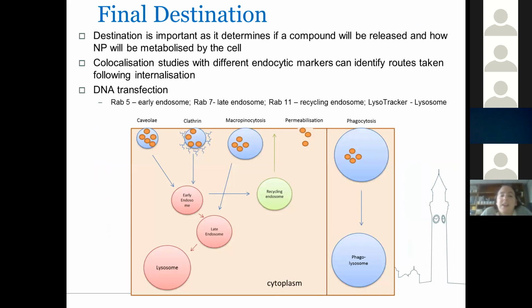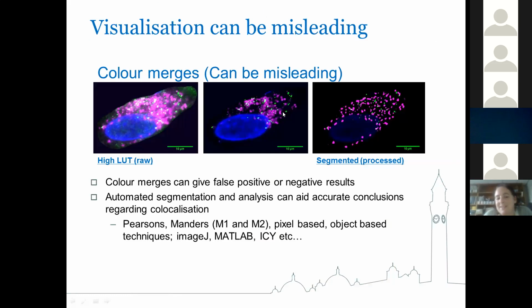We then went on to look a little bit at the final destination, so where the particles go following uptake. And again, we were able to use a range of different fluorescent markers. So the RAB signaling pathway, different variants of RAB localized to different organelles. So RAB5 goes to the early endosome, RAB7 goes to the late endosome, RAB11 goes to the recycling endosome, which basically then means that the particles will get transported back out of the cell. And we also used LysoTracker for the lysosome. So we were looking to correlate where the particles were relative to each of these fluorescent signals.